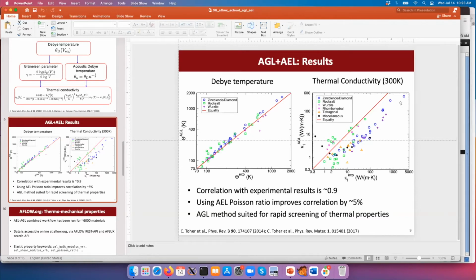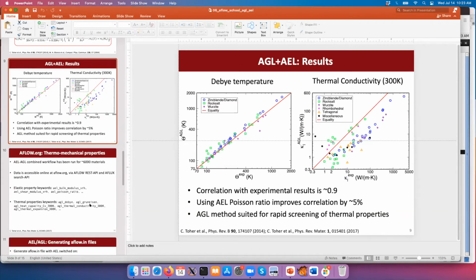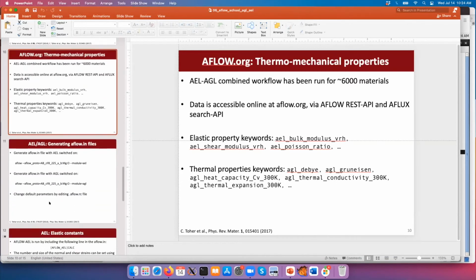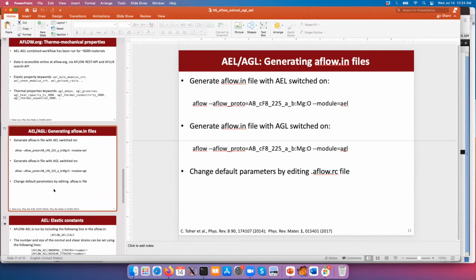Okay. Just to add a little bit to that, if you don't include all scattering mechanisms, you actually overestimate your thermal conductivity too. For example, boron arsenide has a lot of four-phonon scattering. So if you only include three-phonon scatterings, you get a huge thermal conductivity, but the actual experimental values are much lower. Because scattering reduces thermal conductivity, if you don't include all scattering mechanisms you will get an overestimation of the thermal conductivity, not an underestimation. Yeah. Okay.